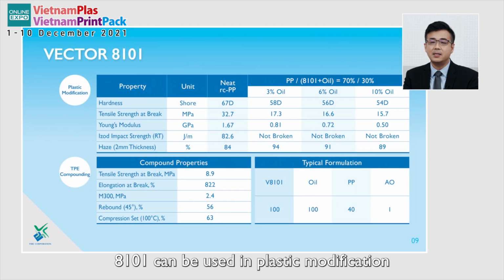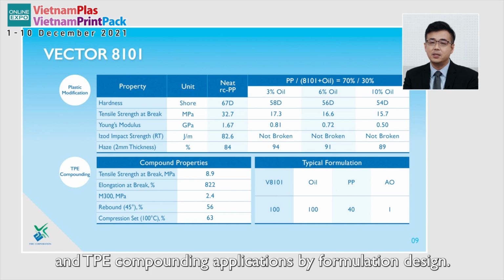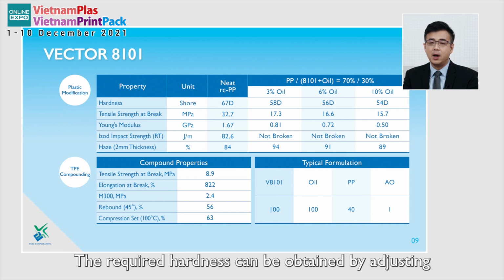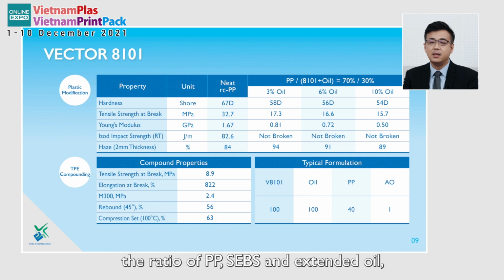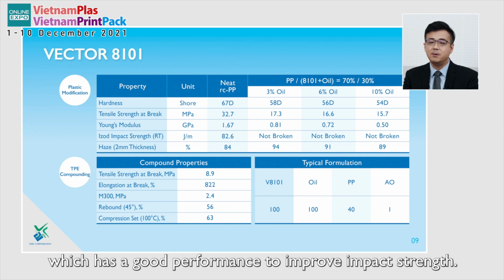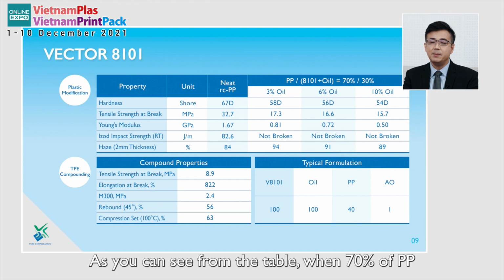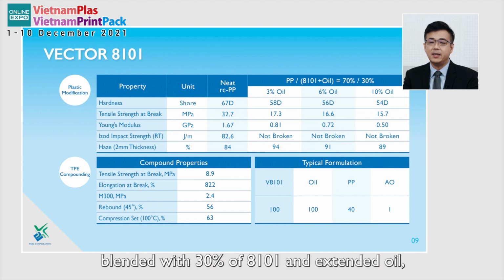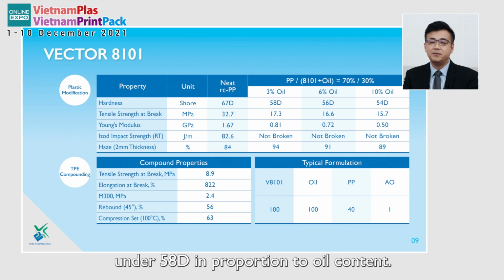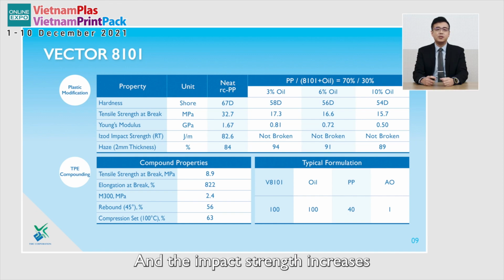8101 can be used in plastic modification and TPE compound application by formulation design. The required hardness can be obtained by adjusting the ratio of PP, SEBS, and the extended oil, which has a good performance to improve impact strength. As you can see from the table, when 70% of PP is blended with 30% of 8101 and the extended oil, the hardness of PP 67D can be reduced to under 58D in proportion to oil content. And the impact strength increases from complete broken to non-broken.